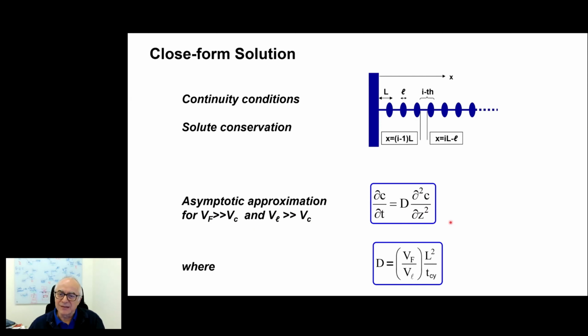So effectively, this back and forth with mixing in every cycle is a diffusive process, but with an accelerated diffusion coefficient. And what is the effective diffusion coefficient? It is the length scale of the system, which is the center to center of each lacunae, squared, divided by the period of every cycle. And it is magnified by the volume of flow going in and out compared to the volume of one lacunae. Therefore, the more fluid invades in every cycle, the faster this diffusion process becomes. What an elegant, simple equation.